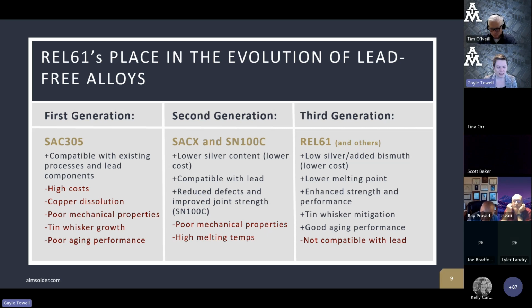It tended to perform fairly well, reduce defects, and improve joint strength, but it has a higher melting temperature. So tin lead has a lower melting temp than a lot of our modern solder alloys. And part of what people try to do is get back to that lower melting temp. But usually when you do that, you start sacrificing a lot of reliability and other things. But lower melting temperatures can be nice for production because of lower energy costs, and you're also less likely to damage your components and your substrate and all of that. So SN100C tended to outperform SAC305 and some of the SAC alloys in certain situations, but it's also a higher melting temperature. It became widely adopted in wave soldering applications, less in surface mount, because of that melting temperature.